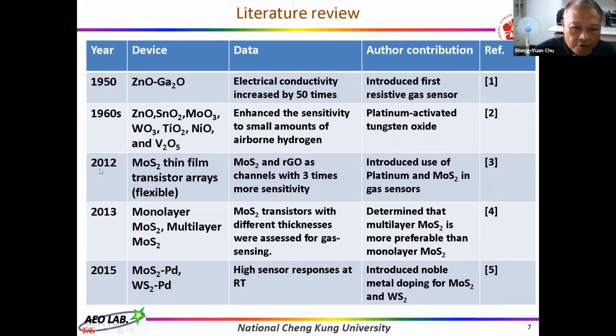In 2012, MoS2 thin film transistor arrays were fabricated on flexible substrates, and the authors introduced the use of platinum and MoS2 in gas sensors. In 2013, the authors determined that multi-layer MoS2 is more preferable than monolayer MoS2. And also in 2015, the authors introduced noble metal doping for MoS2 and WS2, and these devices detected hydrogen at room temperature.